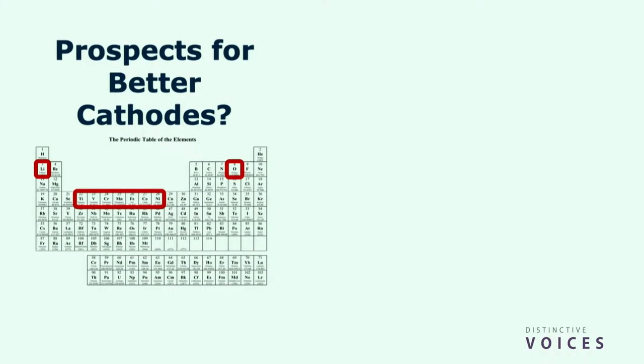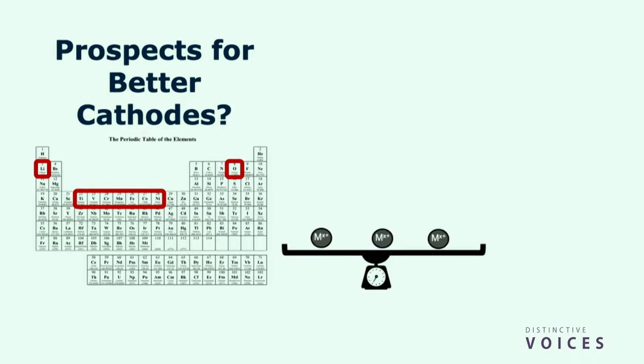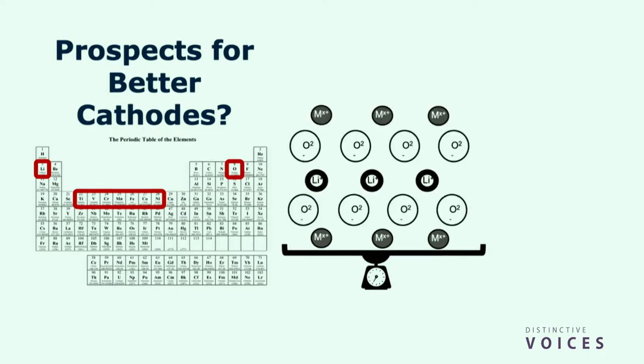They're all next to each other on the periodic table, have similar densities. So when we take these elements of similar densities, similar compositions, they all crystallize in more or less the same crystallographic orientation. Therefore, they all have the same weight. Basically, we're kind of stuck in a box. The maximum theoretical capacity of a cathode of any kind of crystalline compound with those four elements, manganese, iron, cobalt, or nickel, is about 280 milliamp hours per gram.